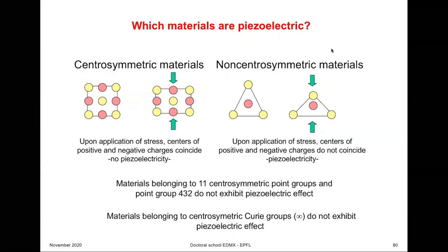When we apply a pressure, which is also centrosymmetric, it is not possible to produce a dipole moment. Pressure on both sides is the same. And remember that the piezoelectric coefficient is equal to the change of polarization with pressure. Now, in centrosymmetric materials, polarization is 0 to start with, and application of, for example, tension or compression cannot induce a dipole.